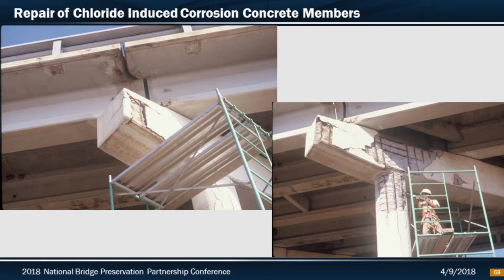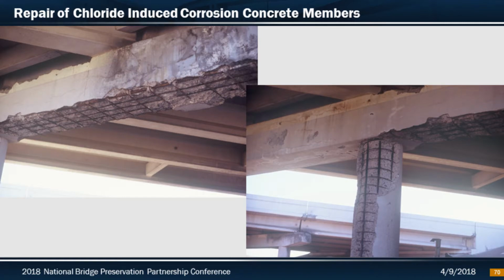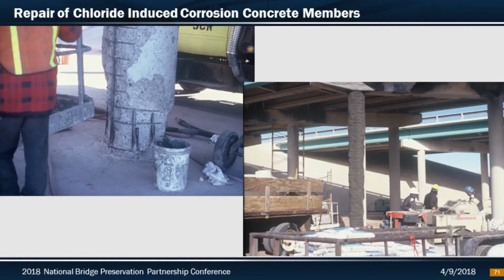Extreme concrete deterioration. Bottom soffits of bent caps were torn up. But like we've mentioned, come in, remove all the unsound concrete, try to remove all your chloride contaminations. Picture on the left, you can see the steel has been blasted clean, got rid of all that surface corrosion.